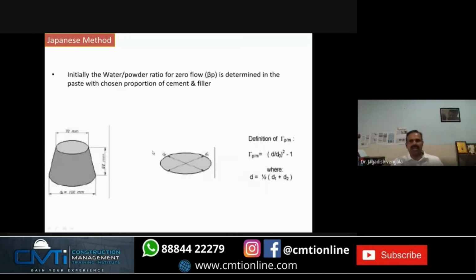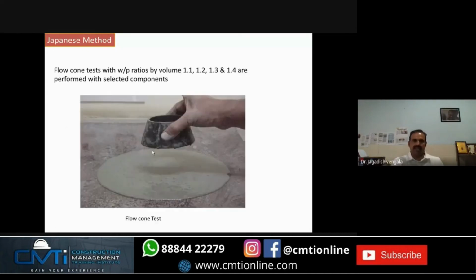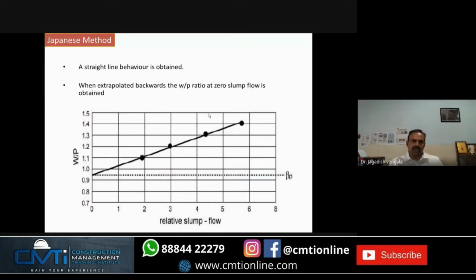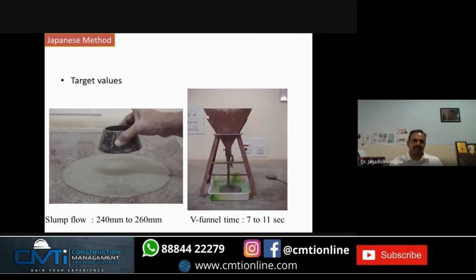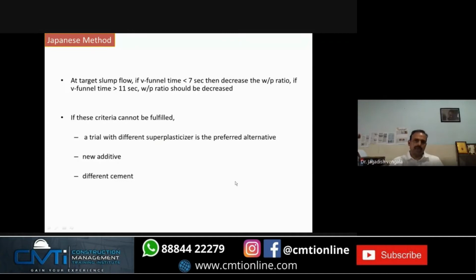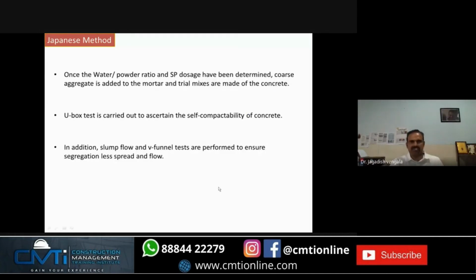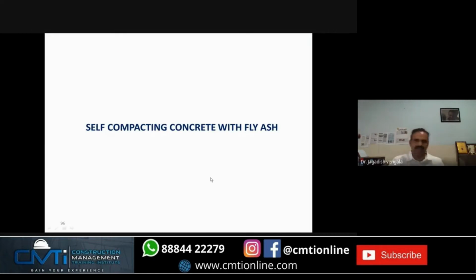So basically the method goes like this. I'm not giving too much importance here because this is completely the mix design part of it. Using the flow test, you measure the water powder ratio, how much water to powder ratio it should be. Based on that, you decide the water powder ratio. Based on the V funnel and flow cone test, you decide the mortar. And then superplasticizer is added, and then you do the regular slump flow and whatever tests for concrete. I'm not going into detail because it's a detailed explanation of the mix design. I've just given a glimpse of the Japanese method.